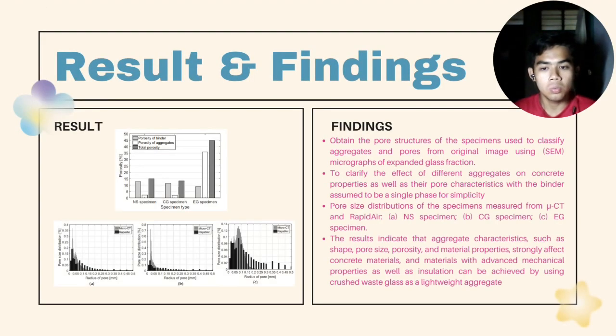For Article 2, we obtain 4 graphs for the results and findings. Firstly, we obtain the pore structures of the specimens used to classify aggregates and pores from the original image using SEM, which is the Scanning Electron Microscopic micrograph of expanded glass fraction. It is to clarify the effect of different aggregates on concrete properties as well as their pore characteristics, with the binder assumed to be a single phase for simplicity.